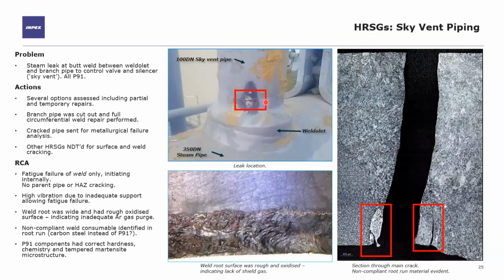When this crack occurred, there was a lot of debate internally as to whether we should do a localized temporary repair or a full circumferential cutout and a proper, permanent repair, if you will. Looking at the pipe in the field, it's pretty obvious that there's a fairly long run of inadequately supported pipe above it. When that silencer was operating, when the control valve was open, it was known that this was shaking a lot. So it wasn't surprising, and it was confirmed in the lab that it was a fatigue failure.